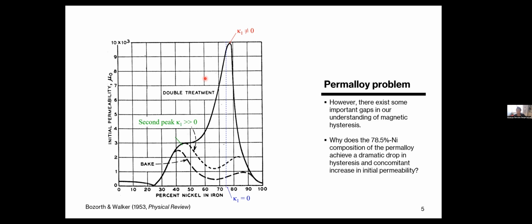Because if you think of a magnet, they have other material constants, and I'll briefly touch on them when I come to the modeling side of things. You have something called the magnetostriction constant, and something called the saturation magnetization, and all of them we suspect play a role in this magnetization reversal. While anisotropy could be playing an important one, we believe that the reason you see certain peaks at which the anisotropy constant is, or we hypothesize is, not zero, is because it's a delicate interplay between a variety of these constants.